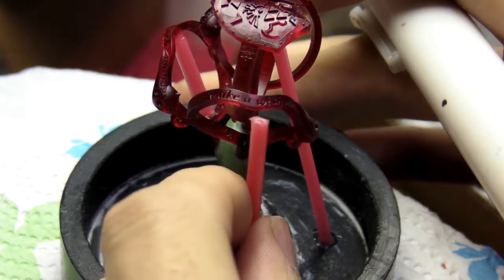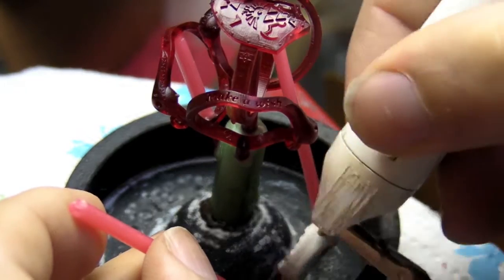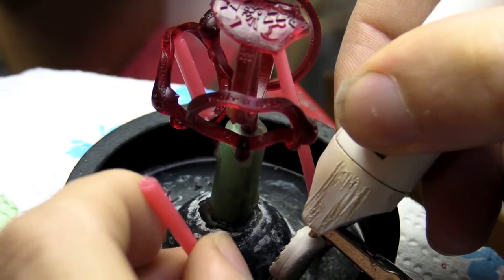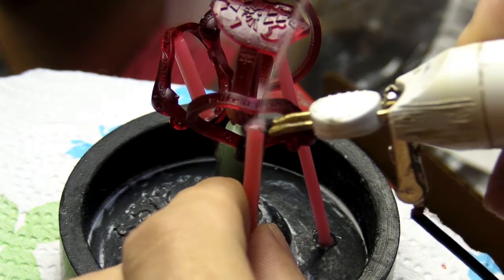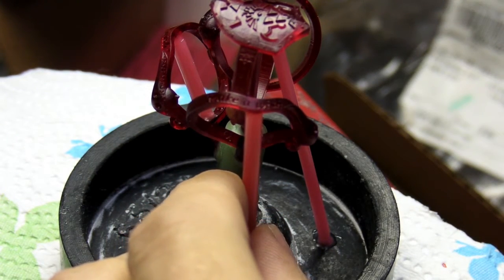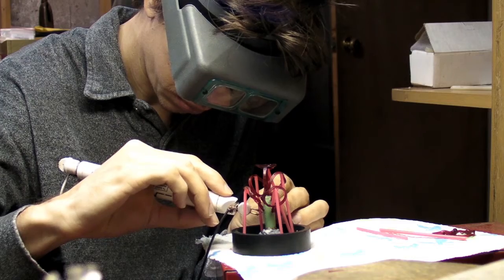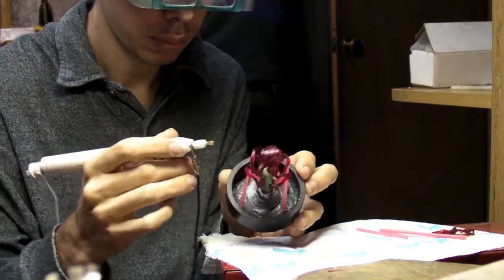I add vents to the pieces so I can vacuum out any ash residue that might remain after burnout. It's an extra step, but it just ensures a clean casting. I also use PlastiCast investment, and use boric acid to strengthen that mix even further. There's all sorts of little tips and tricks to help improve the burnout and casting of these resin parts.